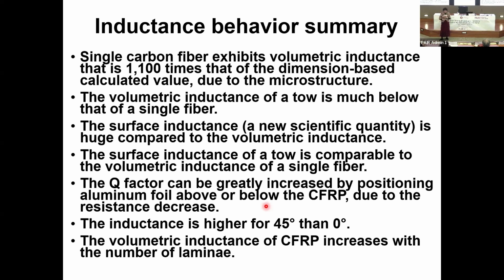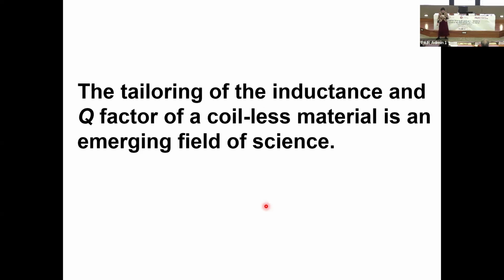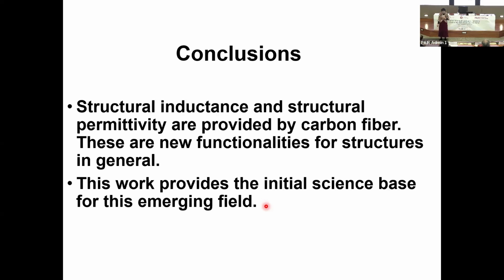The Q factor can be greatly increased by positioning aluminum foil above or below the CFRP due to the resistance decrease. The inductance is higher for 45 degrees than 0 degrees. The volumetric inductance of CFRP increases with the number of laminae. The tailoring of the inductance and Q factor of a coilless material is an emerging field of science.